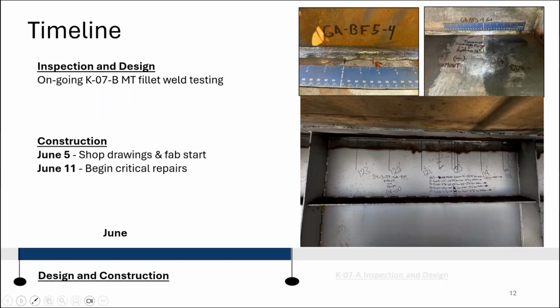Next, we moved into design of the permanent repair and construction of those critical repairs. So at this point, as I stated, we started seeing these little transverse cracks in the fillet. This is the web here, and this is the flange. So we started seeing the same hydrogen cracking along transverse cracks along that fillet weld. As we removed more and more paint, it became clear that this was prevalent. So you can see these black lines in this picture. All of those are transverse cracks in the fillet weld. And that really changed how we were going about the repair and whether a global or local solution was necessary.